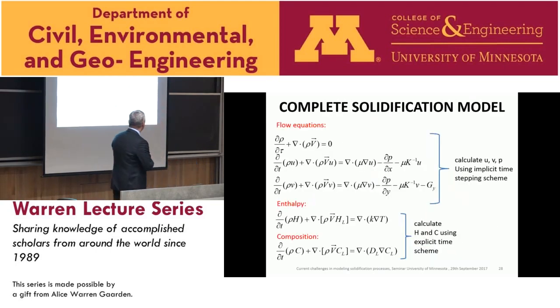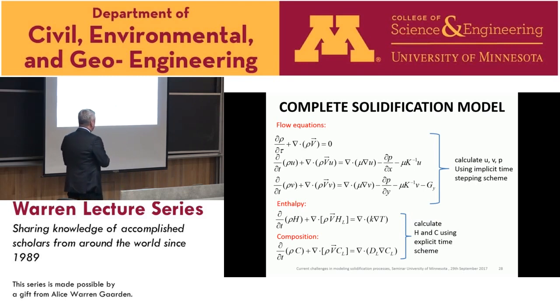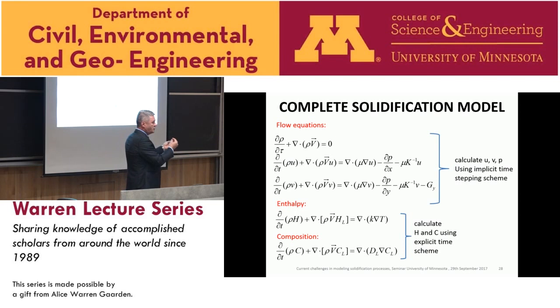And this is a complete solidification model. The flow model is the same. The only change is in G. And G is body forces, usually in fluids because of thermal or solutal contraction of the liquid. So if the liquid becomes cooler or hotter, the differences can cause buoyancy forces. We are using the Boussinesq approximation. Or if the liquid becomes richer with solute, that can also cause changes in the density.